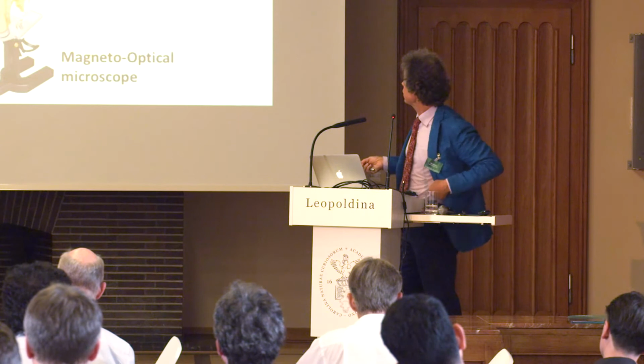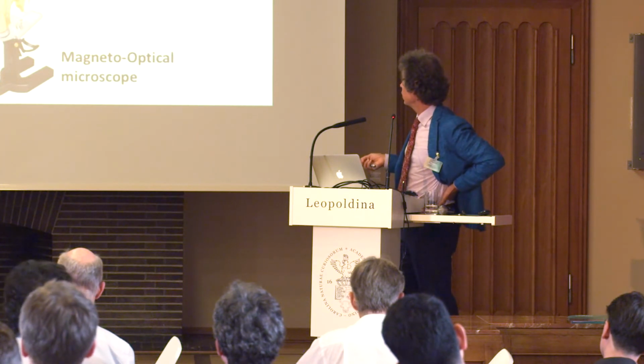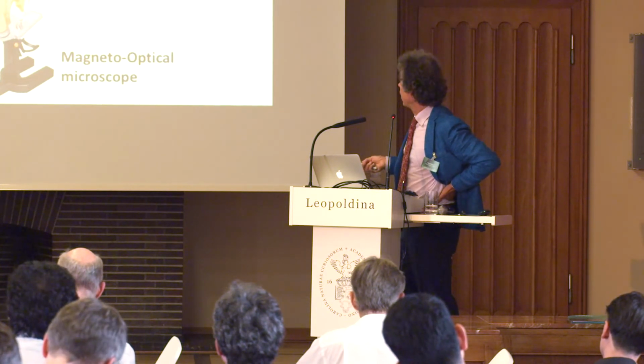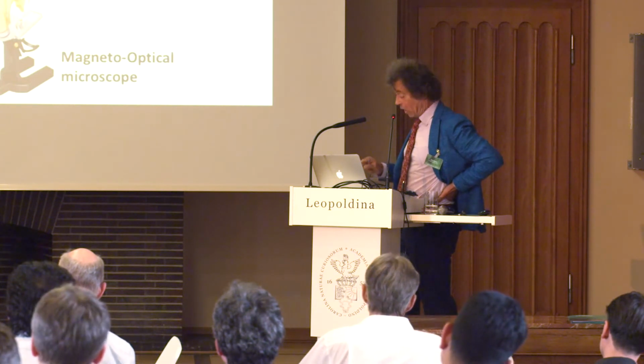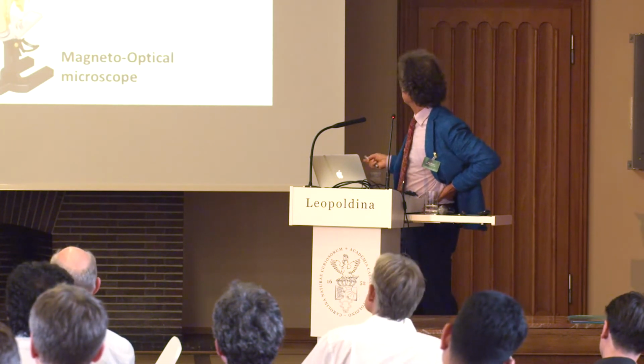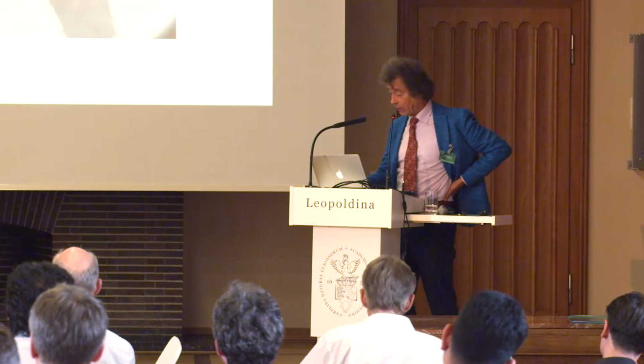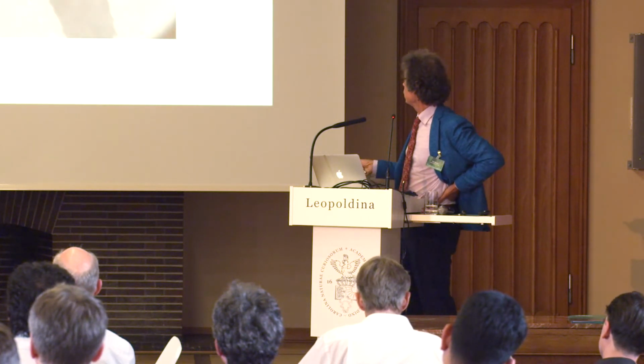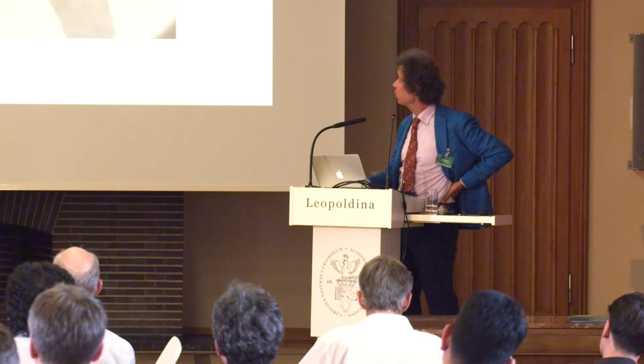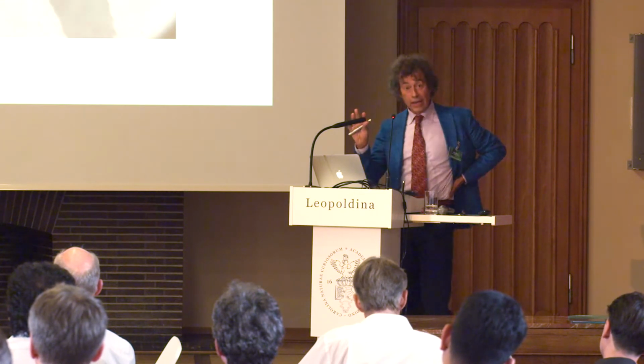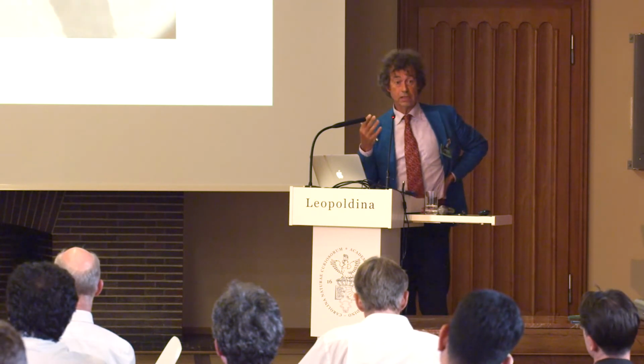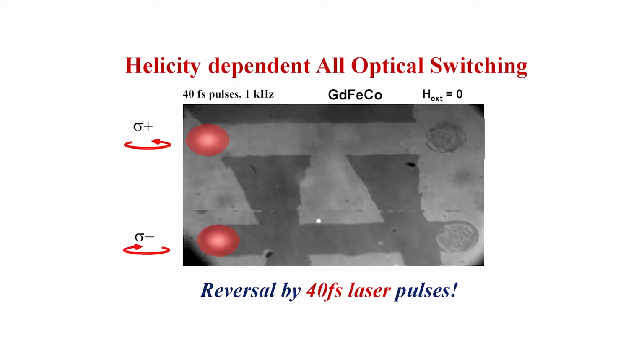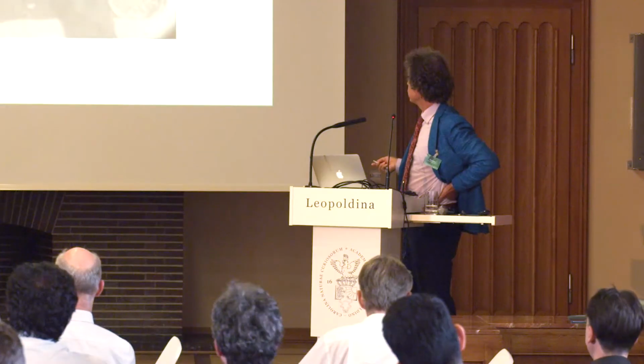And these are the domains that you can then visualize using magneto-optical effects, like the Faraday effect. So this is the magnetization up or down, and then we put femtosecond laser pulses on that. Now we move a femtosecond laser pulse through these domains, and we discover that you can actually use these light pulses to reverse the magnetization. If you use the opposite helicity, then here you make everything stand up, and here it goes down.